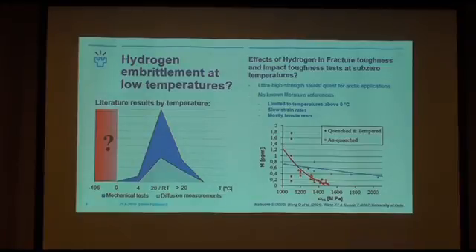And the known literature references. And yeah, I can also challenge you to show some papers from that area, because we didn't find any. So the literature is very limited to temperatures above zero, slow strain rates, and mostly tensile tests. But what we do know is that the higher the strength level, of course, the more prone they are to hydrogen. So if we take, for example, the solubility of hydrogen in pure BCC ferrite, which is around 0.7, we see that we can quite easily run into problems with these steels.